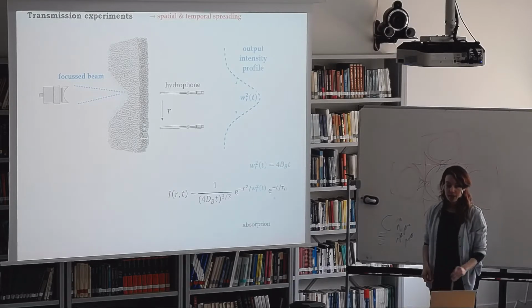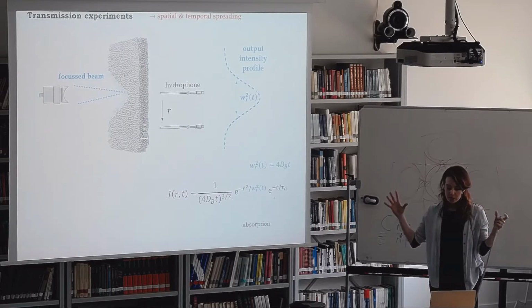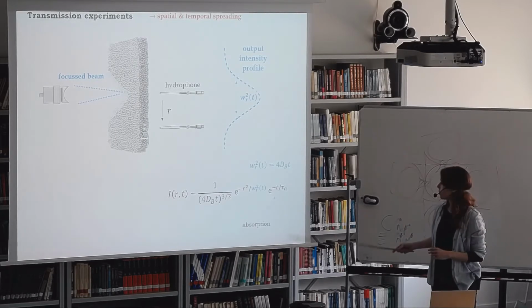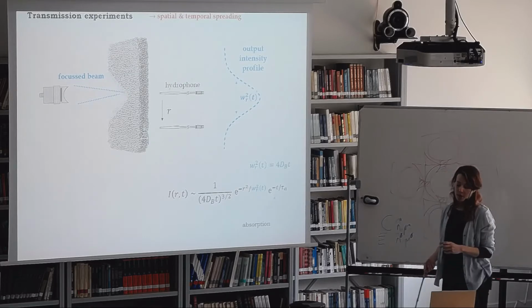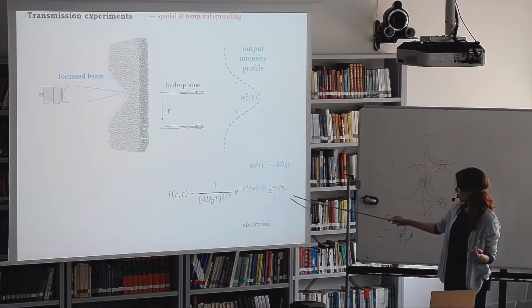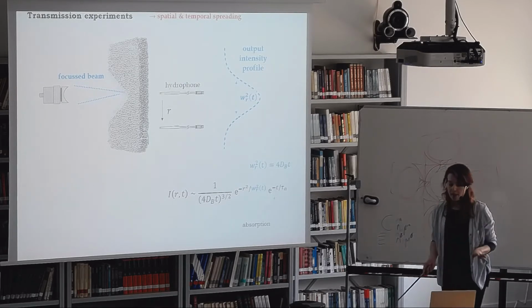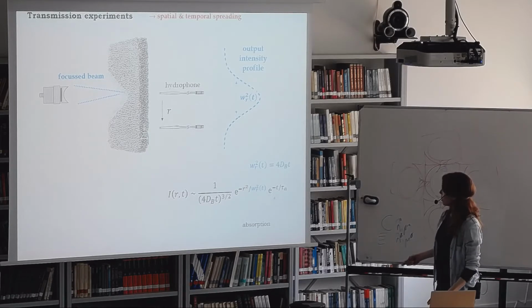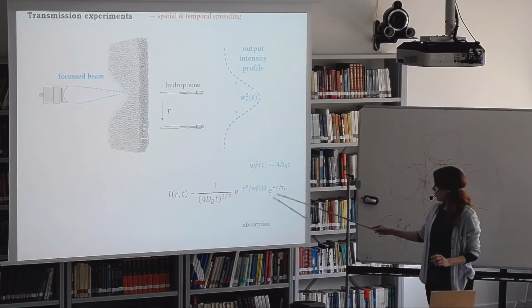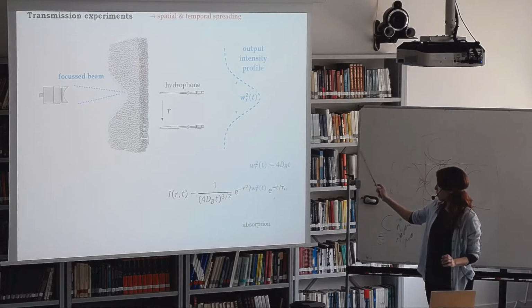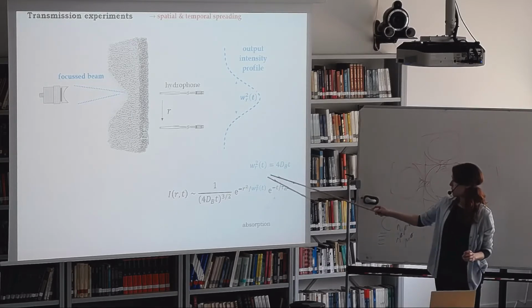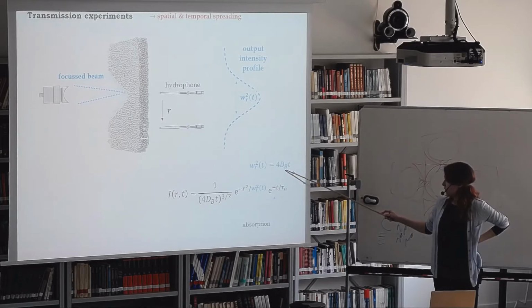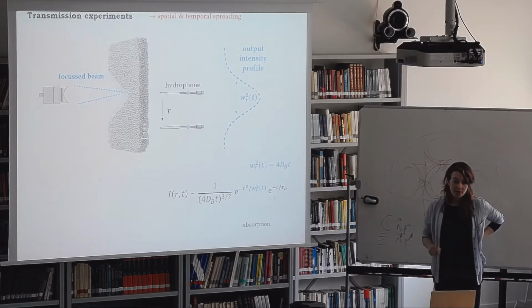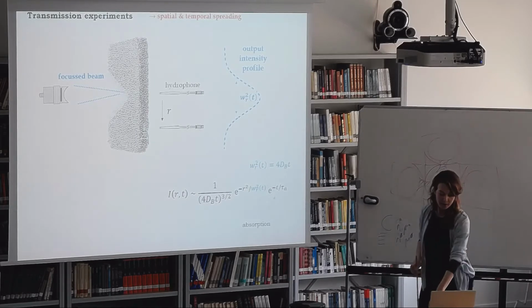So diffusion theory tells us that the spreading of these waves should be Gaussian, as we saw earlier. So something like this equation. Here I've added absorption, which adds an extra exponential decay. And we can characterize the spreading using the width of the Gaussian, which depends on time, as we saw. So the width squared increases linearly with time at a rate which is governed by the diffusion coefficient, like we saw before.